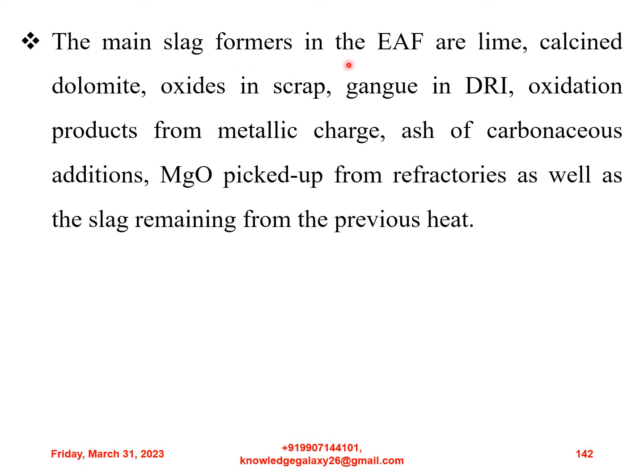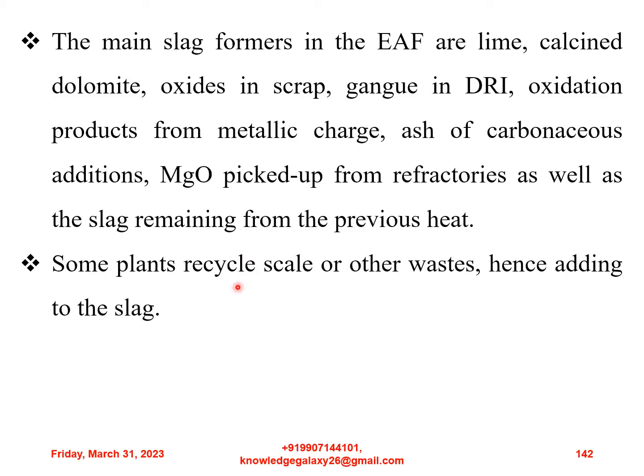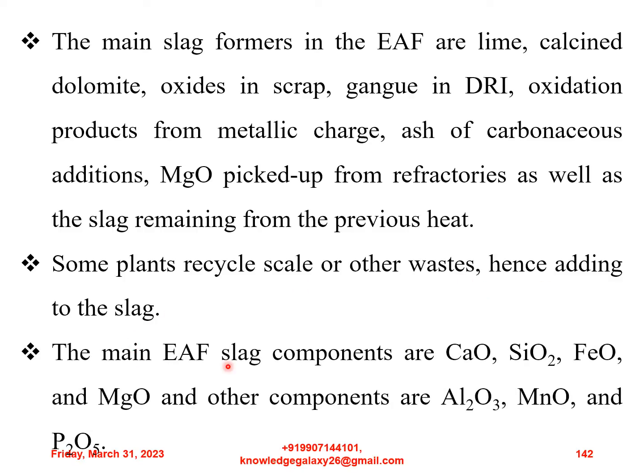The main slag formers in the electric arc furnace are lime, calcined dolomite, oxides in scrap, gangue in DRI, oxidation products from metallic charge, ash of carbonaceous additions, MgO picked up from refractories, as well as the slag remaining from the previous heat. So these are the main sources of slag formers. Some plants recycle scale or other waste, hence adding to the slag. The main EAF slag components are CaO, SiO2, FeO, and MgO, and other components are Al2O3, MnO, and P2O5.